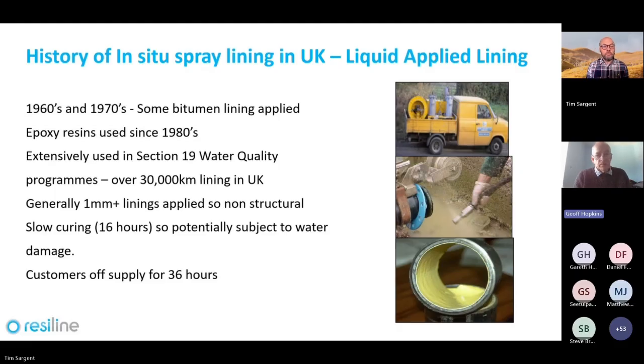The trouble with it was that you needed 16 hours for the epoxy resin to cure. So by the time you'd cleaned the pipe, lined it, allowed it to cure and put it back in service, the customers were shut off for 36 hours, which is something my modern day water industry colleagues could only hope exists instead of the current 3 hours. But as I say, although it was a useful technique, it caused the householders considerable inconvenience.